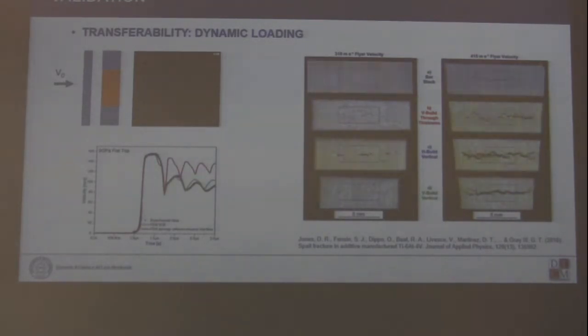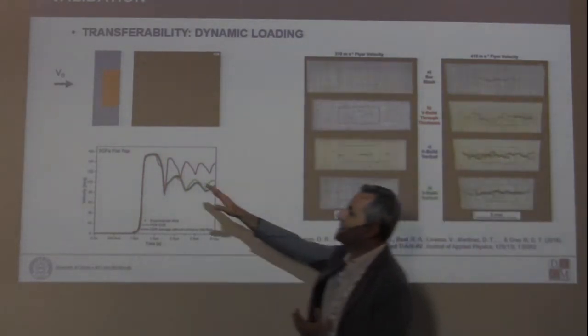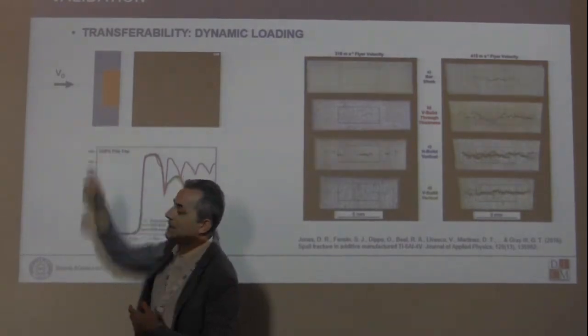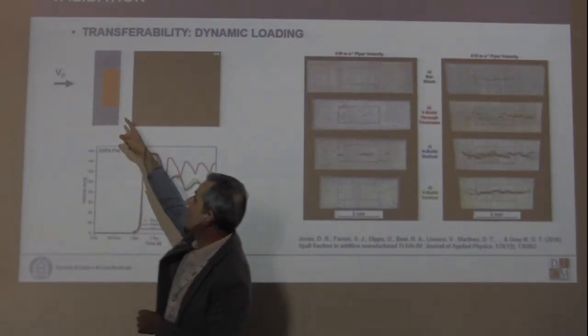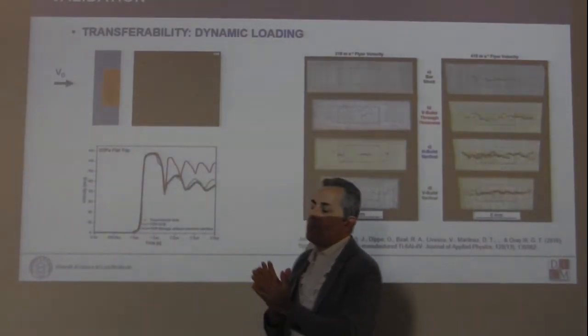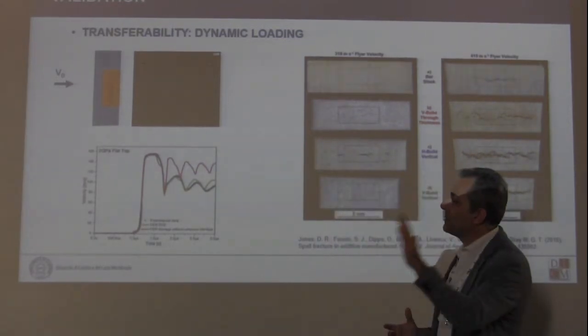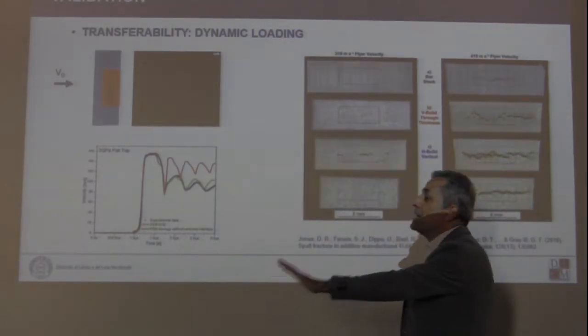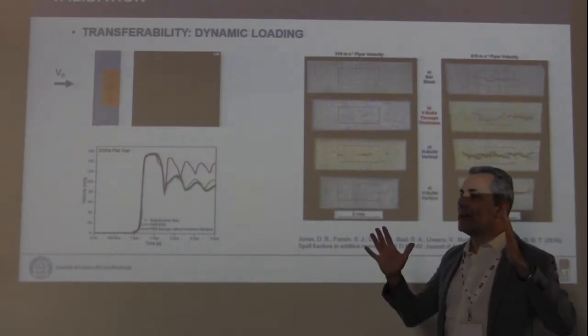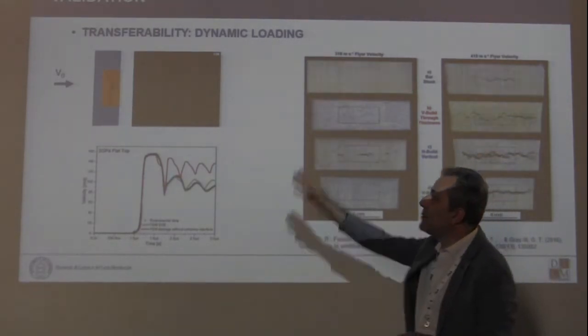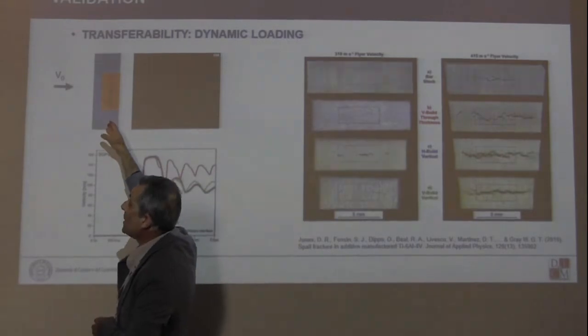And one key point is predicting spall fracture in impact. In the spall, you have a disk impacting another disk. This is the target, a thicker disk. Because of the high velocity impact, the shock wave generated in the material goes as a compressive wave, is reflected as a tensile wave, then builds up with the release wave, and then you have a spall. You have a fracture occurring here.